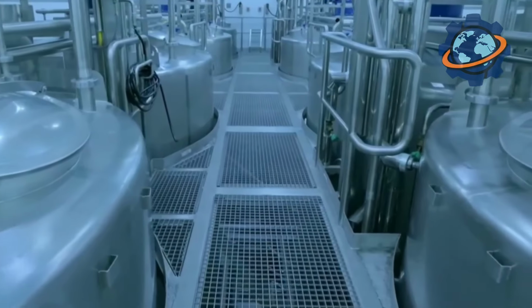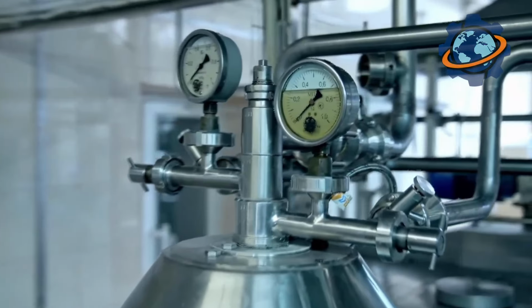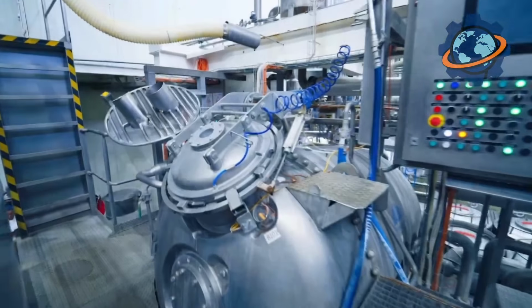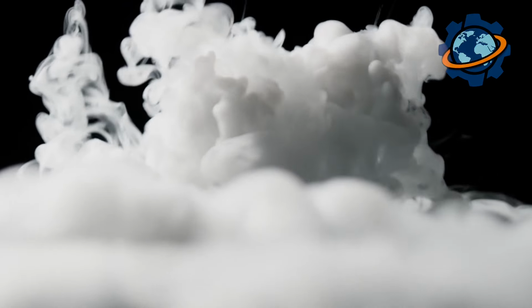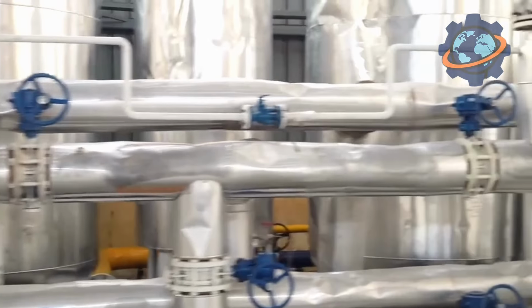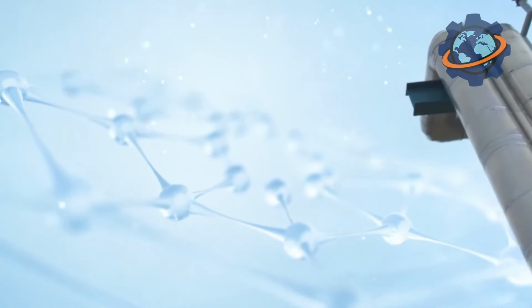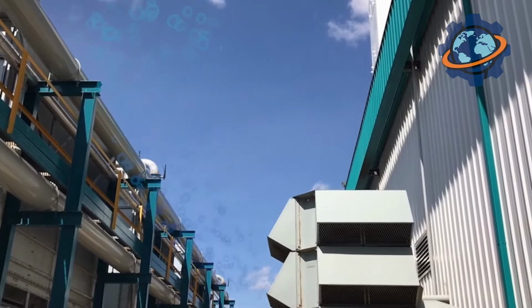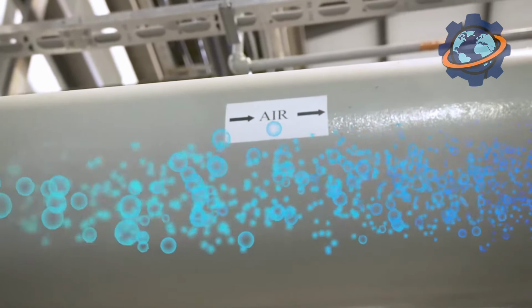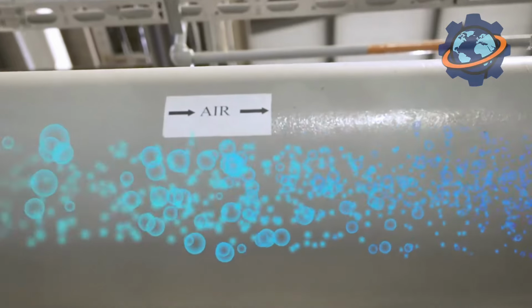They enter a condenser, a special cooled chamber. Temperature in the condenser is around 840 degrees, below boiling point but above melting point of zinc. The vapors condense. Drops of molten zinc settle on the condenser walls, glowing orange. Liquid metal flows down the walls and collects in a receiver. This is crude zinc, contains impurities of lead, cadmium, iron. Purity around 98%. Each furnace produces up to 100 tons of zinc per day.